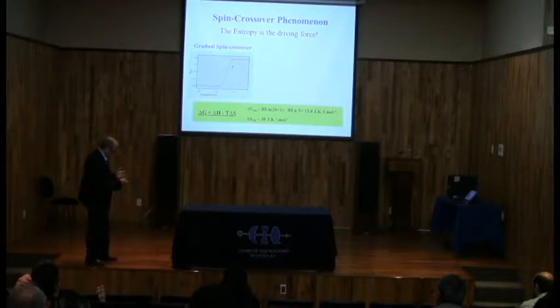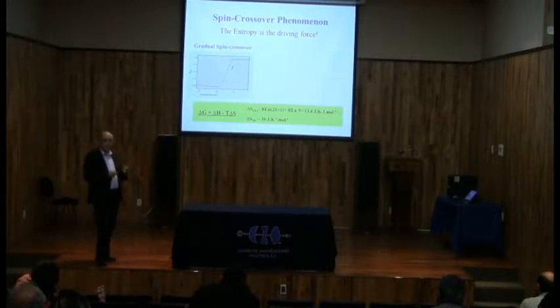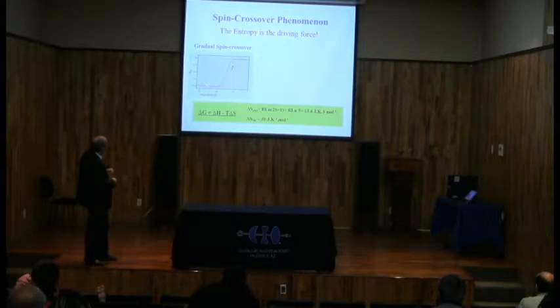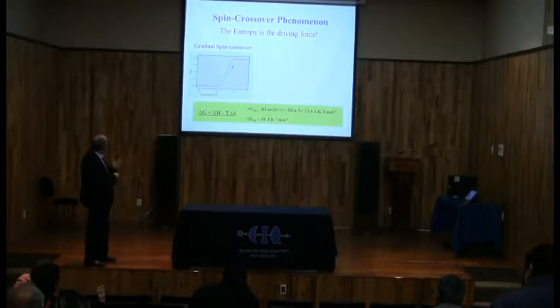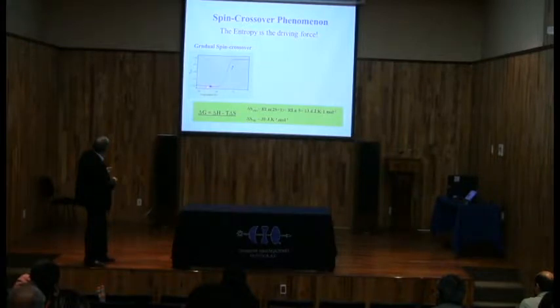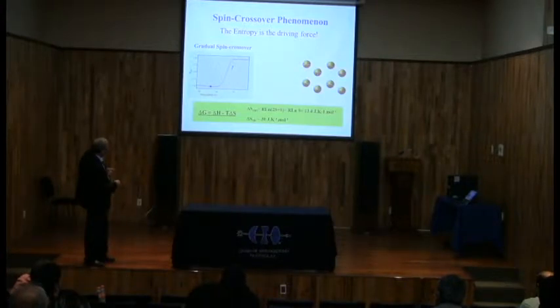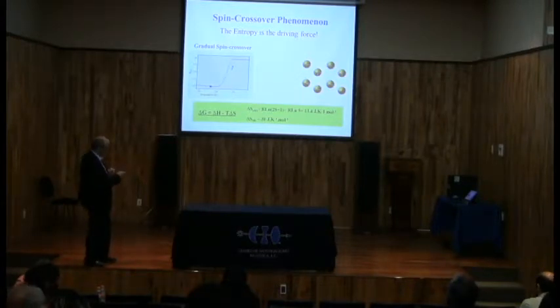Okay? So, if you wish to understand what is the mechanism of switching at the molecular level, we say that the entropy is the driving force. If, for example, we take a system where you don't have hysteresis, the interactions are quite weak. So if you prepare your system in the low spin state here, okay, and you look at the structure of your system, it's in the low spin state, so all the molecules are in the low spin, you have contracted molecules, low volume, okay?